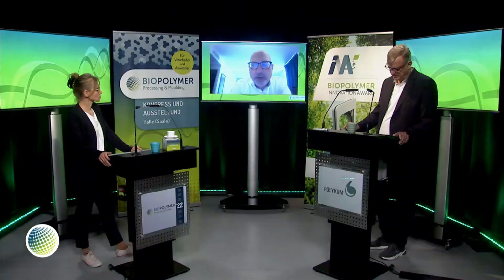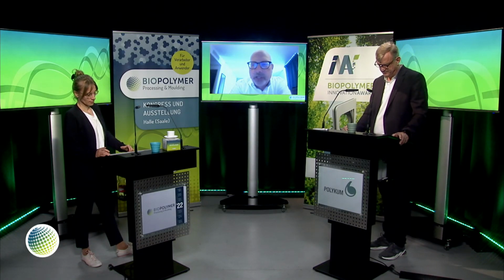So far, we use E. coli as the expression host, and the efficiencies vary between, let's say, 20 to 30 milligrams per liter of cell culture on the lower side, up to 200 milligrams per liter on the higher efficiently producible side.